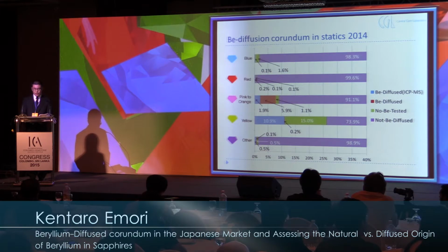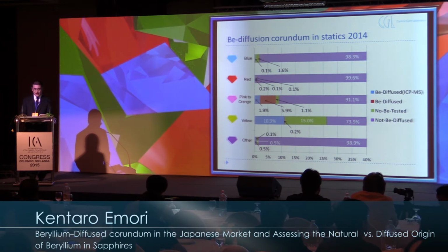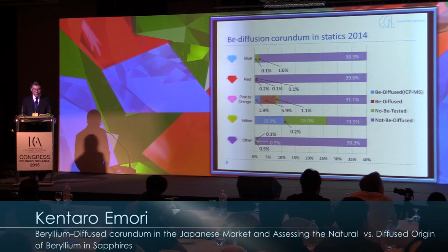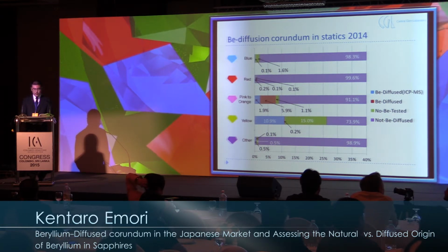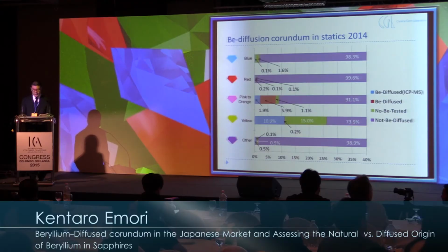Only 0.1 to 0.2% are beryllium-diffused in blue sapphire and ruby, but about 10% are beryllium-diffused in yellow and pink to orange. Many pink to orange beryllium-diffused sapphires could be identified under an optical microscope because they have a surface conformal layer. But very few beryllium-diffused yellow sapphires are identified by optical microscope. The green part in this graph arises because customers can decide whether LA-ICP-MS analysis is done, and it indicates that many yellow corundum did not undergo LA-ICP-MS analysis.